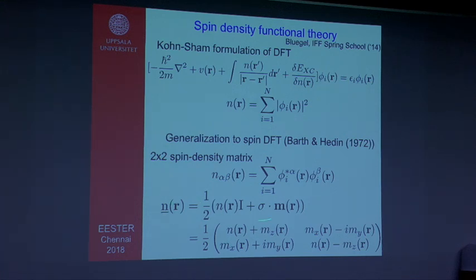And you can write it in a slightly different way, where you have the normal charge density that you get from the normal non-spin polarized density functional theory, and the magnetization density having a scalar product with the Pauli spin matrices. This is a formulation that you can find in many textbooks. If you expand it in a matrix form, it basically looks like this. There's a 2x2 matrix. These diagonal components are basically the Z component of the magnetic moment. And the off-diagonal components have the X and Y components of the magnetic moment, complex quantities. So for spin density functional theory, it's a 2x2 matrix, and it has off-diagonal components. We have to remember that.